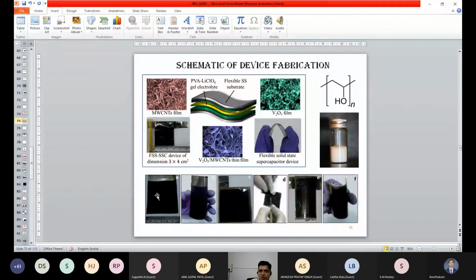This is one electrode coated with the carbon nanotube, which has vanadium oxide deposited on it. We have cut that one. Then we made this certain gel. Then we sandwiched, and this is finally a solid state device which is possible to bend. And here you can see that it is possible to bend this type of device, which is vanadium oxide coated on the carbon nanotube to form the complete solid state symmetric device. Symmetric means what? Both electrodes have the same type. And the area we have used is 3 by 4 centimeter square. This is a larger area.